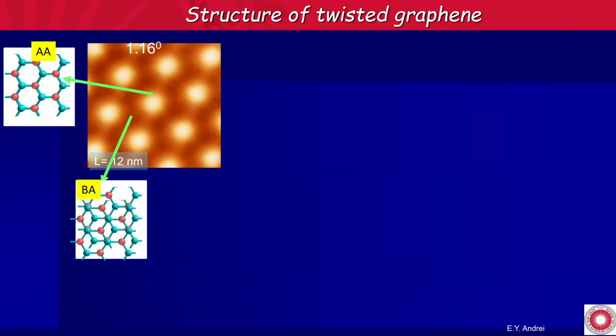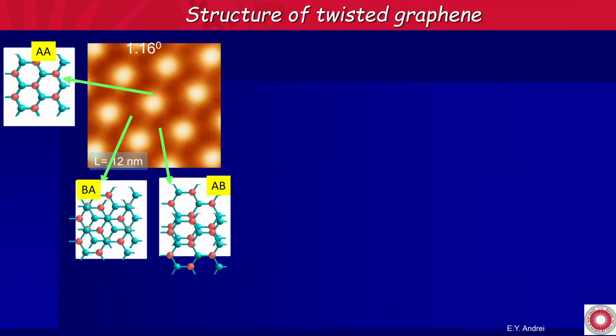So what are we looking at here? First of all, the bright spots that we see in STM are where we have the AA configuration, where every atom in the top layer sits on a corresponding one in the bottom layer. There's a BA configuration where every B sublattice atom sits on the A sublattice in the bottom layer and vice versa. So this is the pattern that you create. So these are the AA regions. When you look at topography, these are bright because the electronic wave function is focused there.